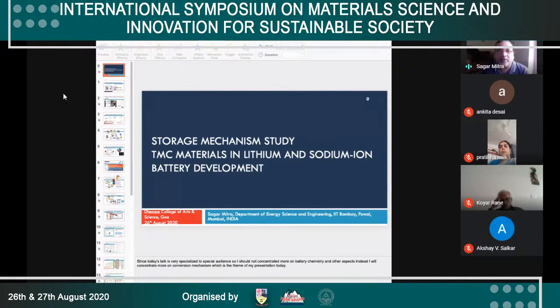The first battery had a problem because of the lithium dendrite issue, and the lithium dendrite issue came from the lithium metal itself. They thought of two solutions. One was to remove the liquid electrolyte and introduce a polymer instead of liquid to prevent that. But it was observed that the polymer also didn't work out, since lithium dendrite formation is there because of lithium. So the second solution was that lithium metal can be removed and an intercalation material put in, and that's how graphite and lithium cobalt oxide came into the picture, and the battery you are using right now is based on those findings.